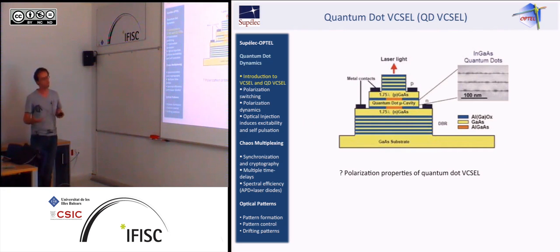Now, about quantum dot VCSELs. This is most probably one of the most common kinds of structure of a quantum dot VCSEL. You recognize what these are, not a question of technology, but these are distributed Bragg reflectors. Basically, these are mirrors. You have the cavity here, which is the active medium of the laser. And inside this active medium, you have the spontaneous growth on each epitaxial layer of these islands that confine the carriers in 3D, these islands of dots. These are indium gallium arsenide quantum dots grown on gallium arsenide. So this is basically a deposition of indium where it doesn't like to be on gallium arsenide, which means strain redistribution and the formation of those islands of dots. And you have these dots filling the active medium.